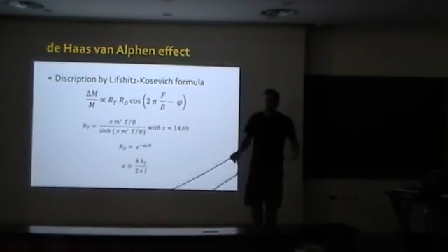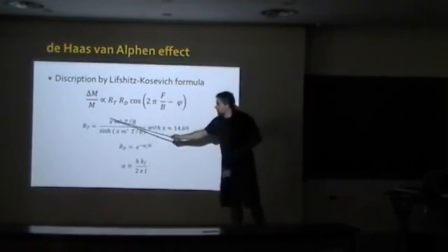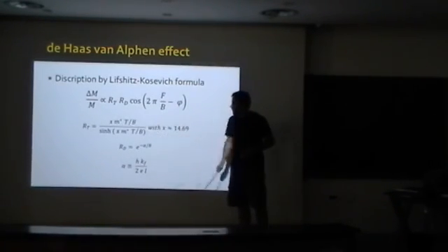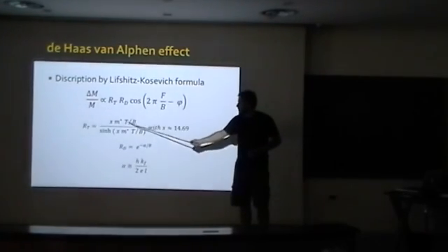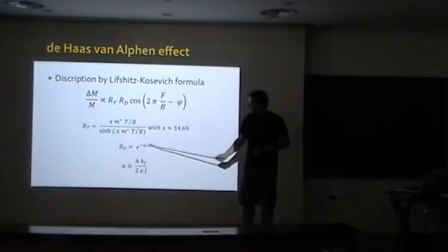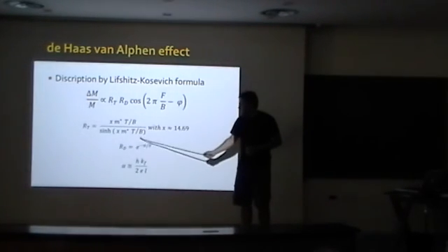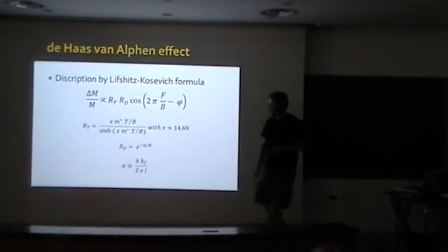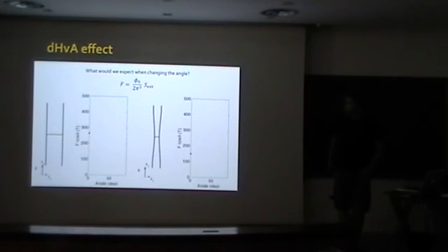There can be a lot more depending on your system, but the two main factors are the temperature damping part, from which we can extract the effective mass of the quasi-particles by keeping the field constant and changing the temperature. Or we can learn something about our mean free path by looking at a constant temperature and looking at how the amplitude changes with field. Okay, what we can learn from that first of all is the interaction-enhanced quasi-particle mass, and what the mean free path is, so how good our sample is.